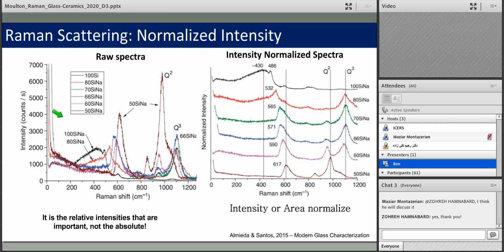One more note on intensity is how we normalize it and how we present the spectra. Here on the left hand of your screen is a bunch of glass spectra that goes from pure silica to 50% sodium. Pure silica is shown in black, and you can see it's very weak and only gives you 200 counts for the experimental conditions where this was run. But as you add more sodium, you'll get a much higher intensity. These differences are related to that polarizability I mentioned a moment ago.